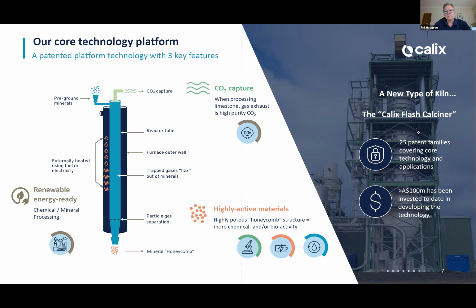What we do is a little different. We have a central reactor tube, and I've got a nice little toilet roll here to demonstrate that. This picture on the right-hand side of your screen is our plant at Bacchus Marsh in Victoria. That was our first commercial scale demonstration facility. The tube inside that little furnace is about 22 meters high and about 1.8 meters in diameter. So it's fairly large, much bigger than this. But essentially we just heat a tube from the outside, up to about 1,000 degrees centigrade.